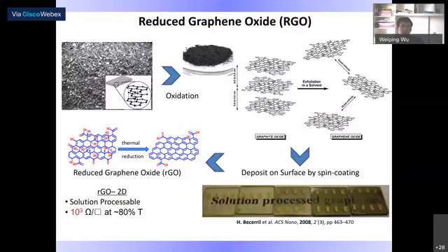There's another kind of method that many researchers have been involved in, using graphene oxide, which is a low-cost material made by a chemical synthesis procedure. What you are doing here is integrating acid molecules in between the layers of the graphite lattice. Then this acid will react with the plane or crystalline domains of the graphene, thereby inducing chemical functional groups as well as defects. So this graphene oxide, or GO, even after reduction, contains a high level of this type of defects.